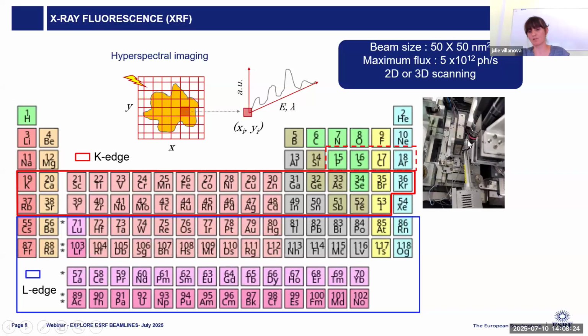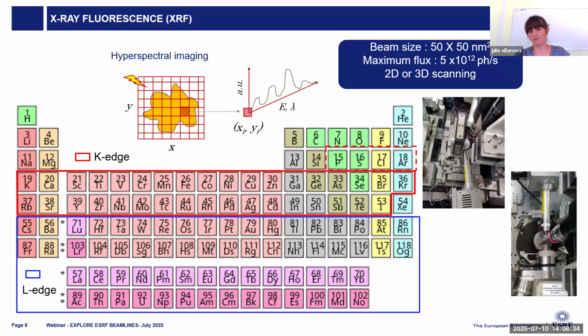You have the piezo stage with the sample mounted there. And then you have the two fluorescence detectors in a reflection mode that will collect the fluorescence signal. We can also accommodate the sample on a rotation stage in order to scan the sample. So you scan a line, you register the fluorescence at each point on the line, then you turn, and so on, in order to reconstruct a 3D slice with the fluorescence distribution, I mean, with the chemical distribution within the sample.